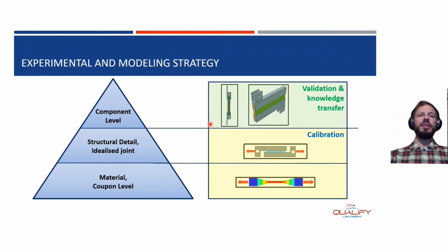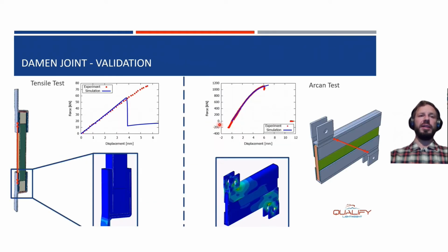in order to validate our models that we have calibrated. Now let's have a look at the first results for the Damen joint, for example. There we have on the left-hand side the tensile test. Here again, you see the tensile specimen. And on the bottom, you see a video of the tensile specimen being loaded, where you see the stress distribution in the joint until the final rupture of the interface or the skin failure that we simulated.